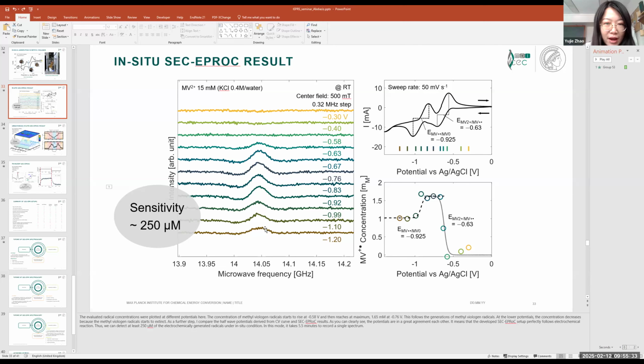Yeah. And also, have you seen any broadening effect due to any of the electrostatic interactions? Surprisingly, no. There are some strange things which I cannot explain currently going on with these, like placing a metal inside an EPR spectrometer. For example, the quality factor doesn't change as much, and when I try to do pulse EPR, I can decouple much better actually with a metal piece inside. Okay. So there are certain things that I cannot explain, but all for the good so far. Like they've been in my favor, which is good.